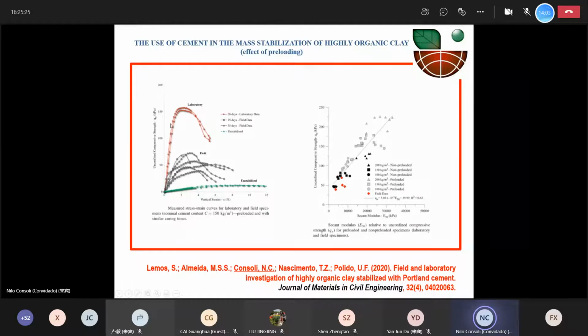here, let's say, and then we can see the difference that we have for specimens that are molded in the lab and mixed in the lab, and the ones that were collected in the field. So that is the difficulty that we have in mixing in the field through this mass stabilization. But even though, it gets much better than the unstabilized material that is quite down here.